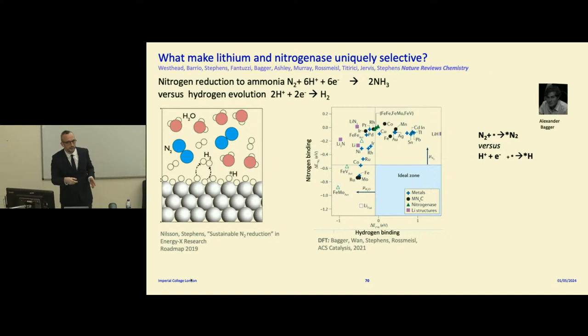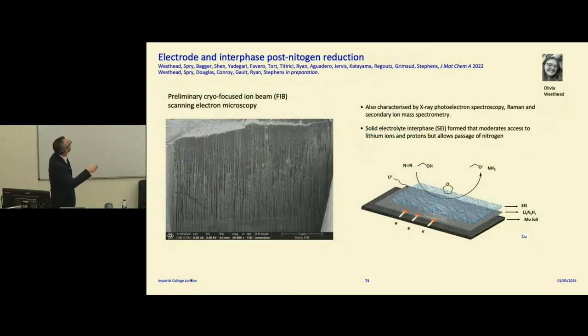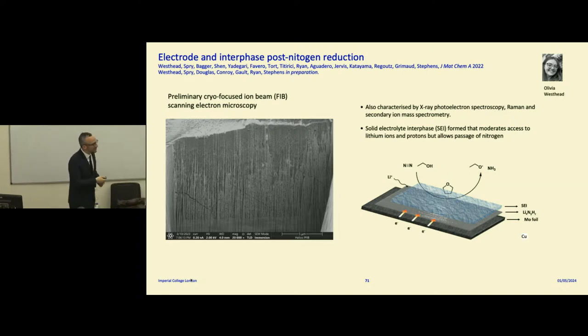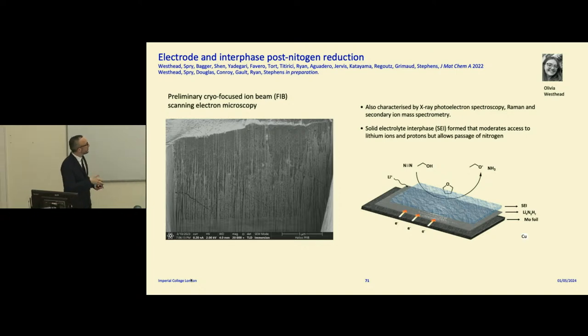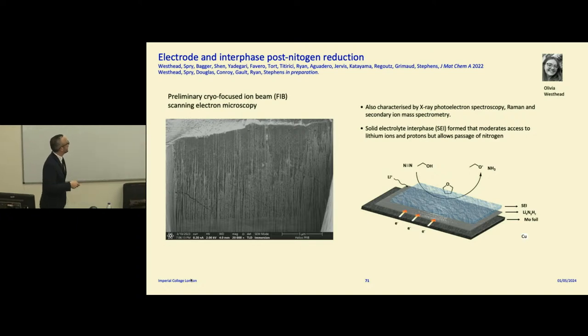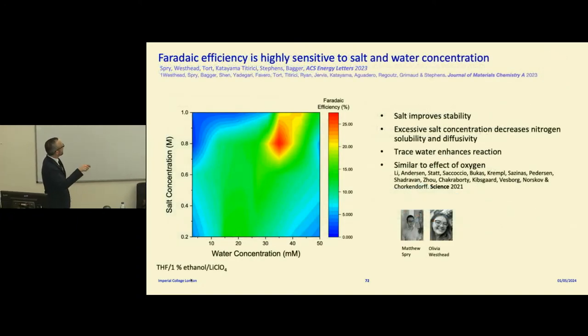So to try and understand how they work, you need to think beyond how we usually think about binding different species, and think about how to tailor the environment around the active site. What we found is work done by Ollie Westhead. She did a microscopy cross-section using our new cryo microscopy sensor and found a very thick layer of a solid between the electrolyte and the actual electrode. Battery scientists know this as a solid electrolyte interphase. So what we think is happening is that this interphase allows nitrogen to go through and moderates access to protons and lithium, so that's how we can make ammonia. This is work done by Matthew Spry and Ollie Westhead.